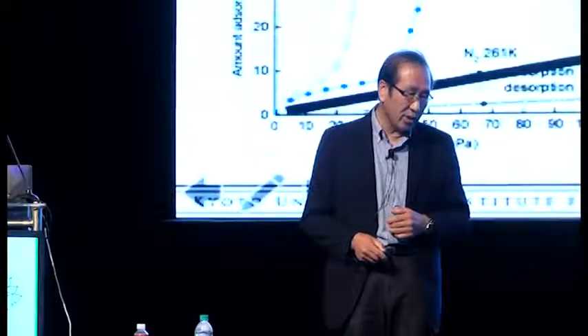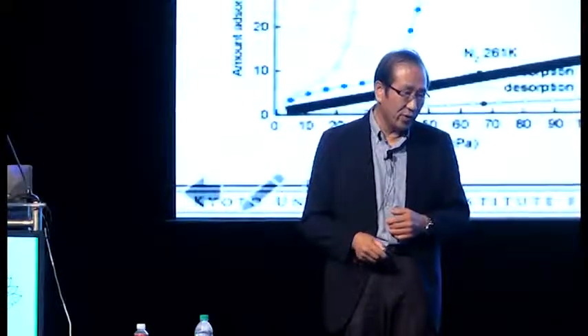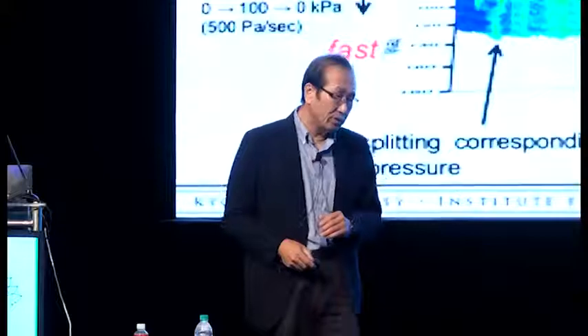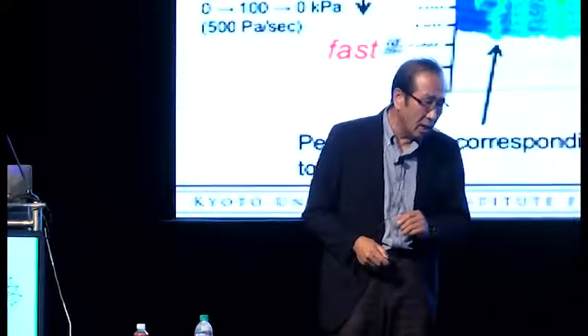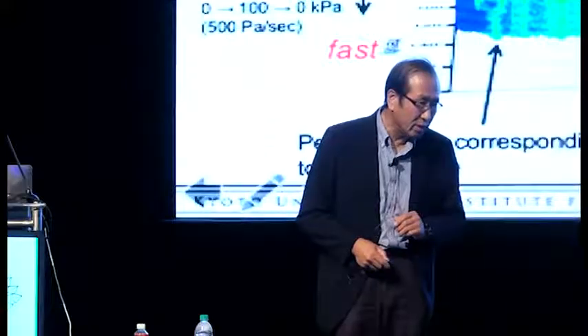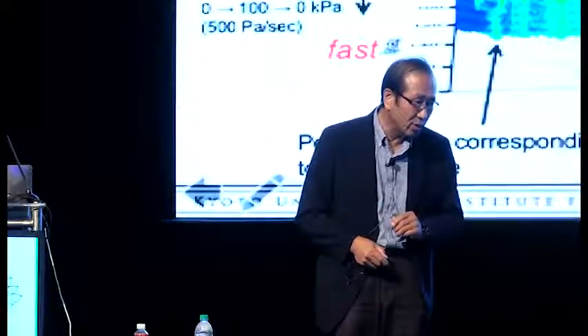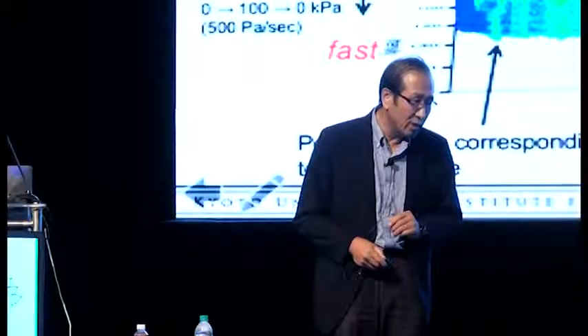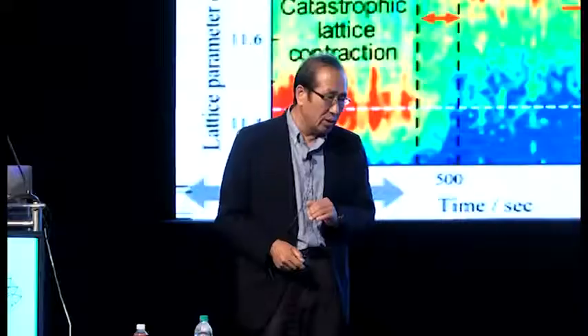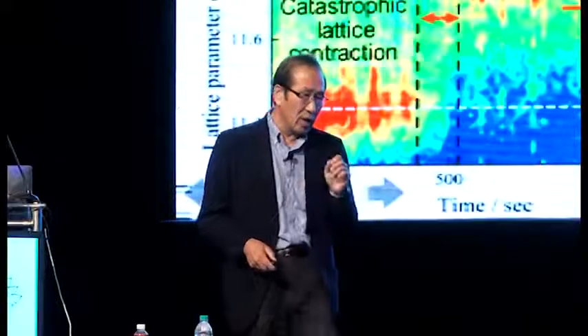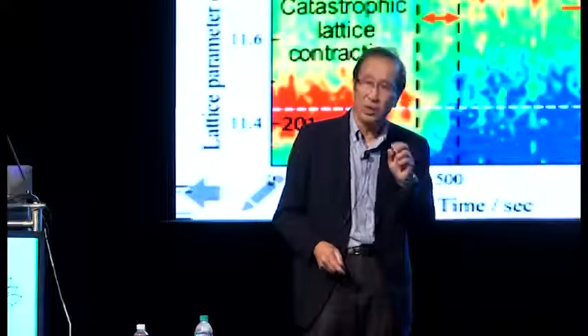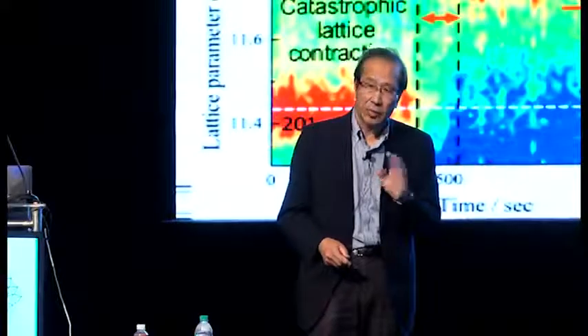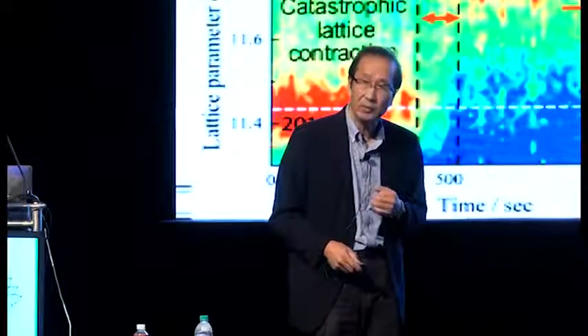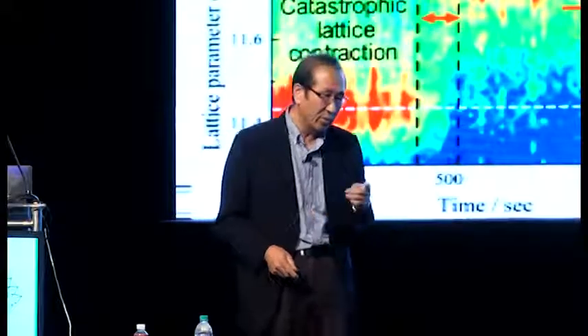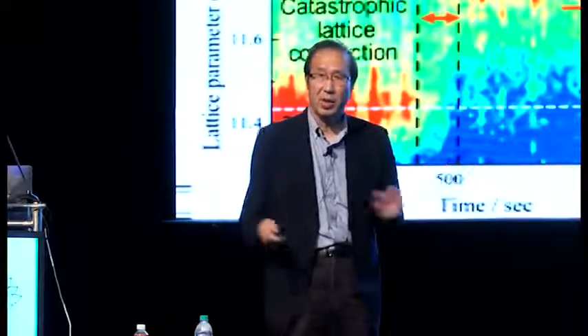This is the final state, and this is the initial state. The diffractions are different because of the different phases. So we observe this one, and we succeeded in getting the transient. Okay, this is the initial state, and this is desorption, adsorption. In between, we have the transient state, like this. This state is completely anisotropic. But still, we need several more data, so it is under investigation. But this is a good sign, using these very fantastic facilities.